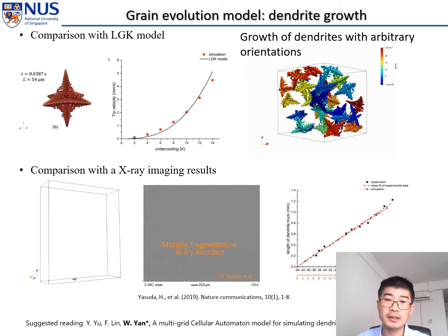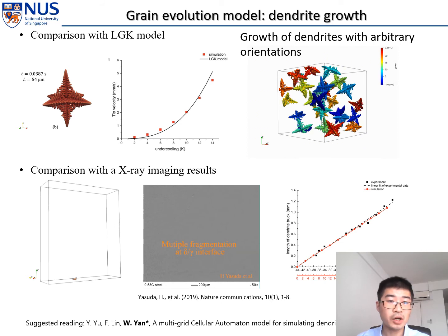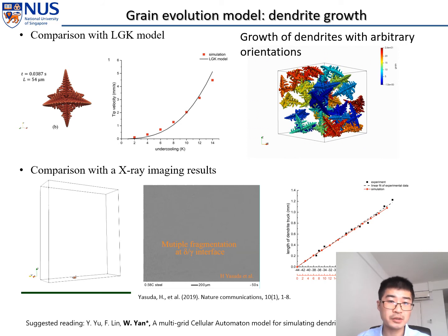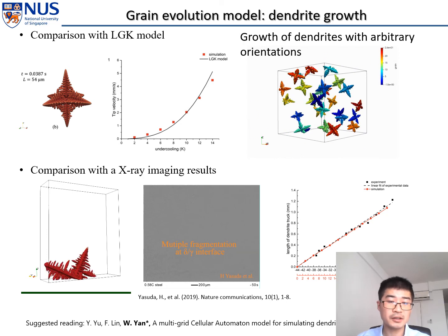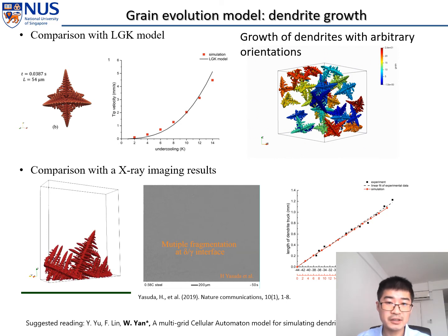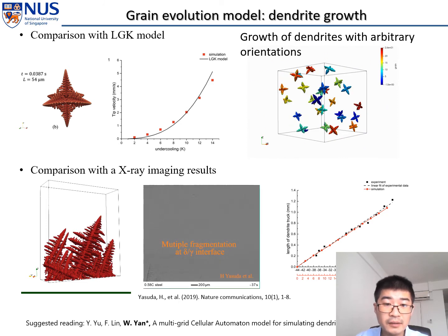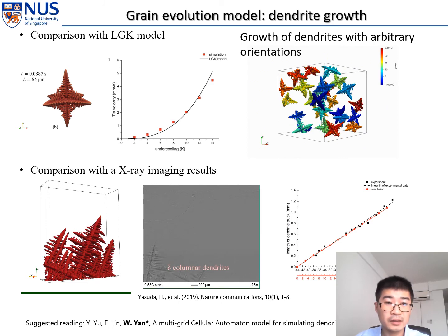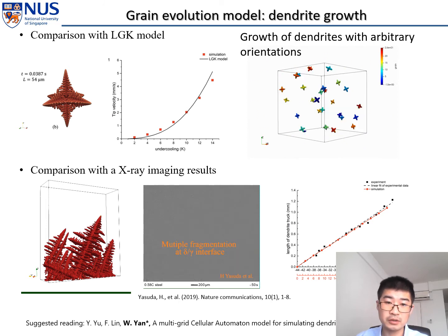And also, we can simulate the growth of dendrites with arbitrary orientations. Furthermore, we validated our simulation with X-ray imaging results for a directional solidification case. And you can see the dendrite growth rate agrees very well with our simulation results.